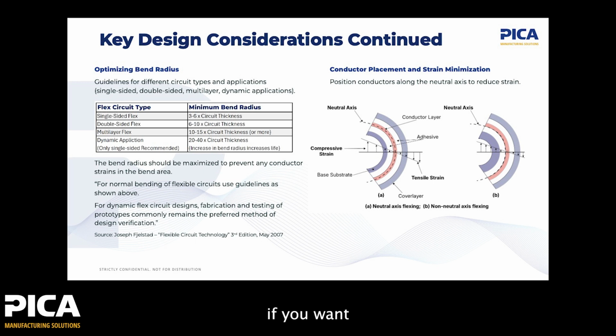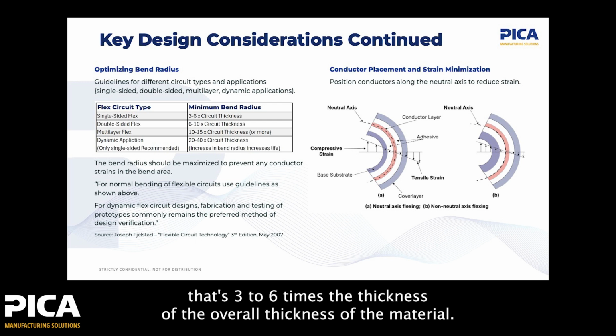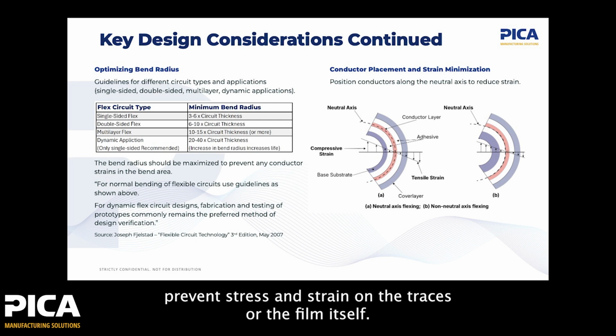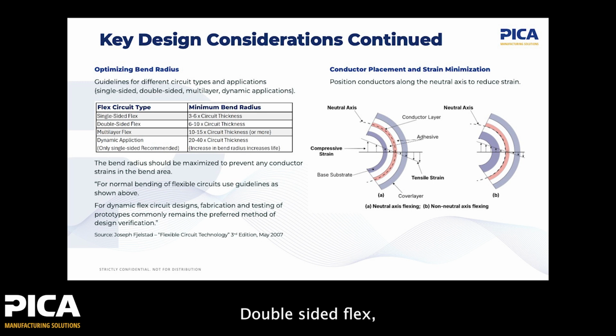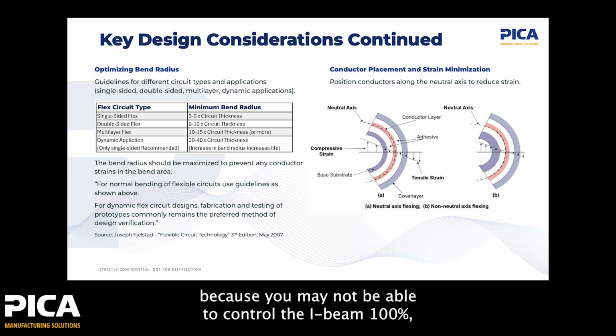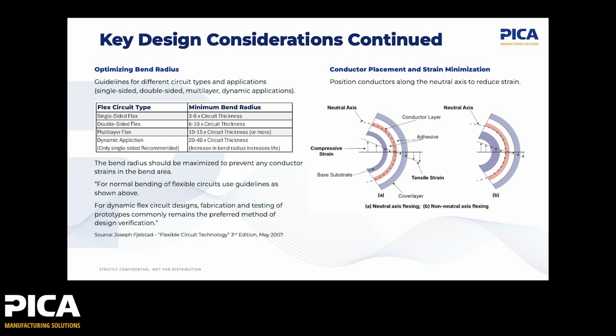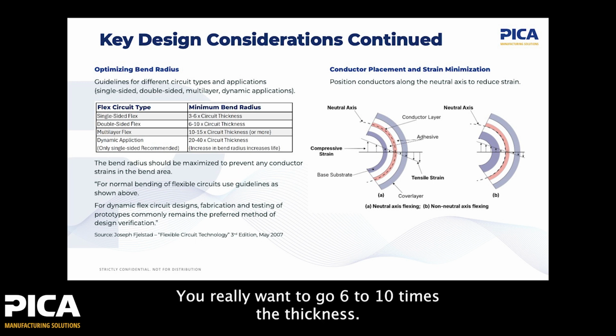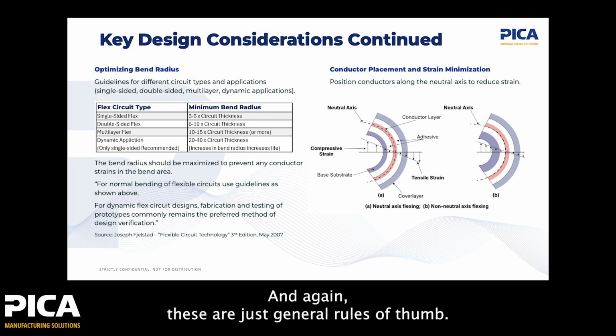Single-sided flex, if you want to bend this flex, you want something that's 3 to 6 times the overall thickness of the material. And this is going to help you prevent stress and strain on the traces or the film itself. Double-sided flex, because there's 2 layers of copper, because you may not be able to control the I-beaming 100%, you really want to go 6 to 10 times the thickness. And again, these are just general rules of thumb.